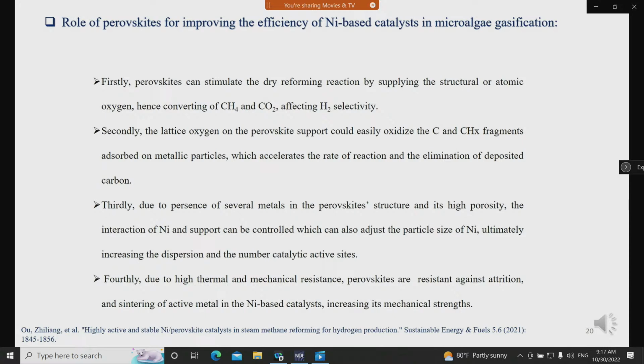Thirdly, due to the presence of several metals in the perovskite structure and its high porosity, the interaction of nickel and support can be controlled, which can also adjust the particle size of nickel. So, the dispersion can be increased, and the number of catalytic active sites also can be increased. Lastly, due to high thermal and mechanical resistance, perovskites are resistant against attrition and sintering of active metals in the nickel-based catalyst. So finally, it can increase mechanical strength.